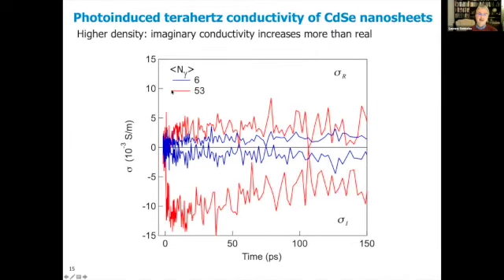Now, if you go to a higher photoexcitation density, so here in the red curves we excited 53 electrons in a nanosheet, so we make 53 photoexcitations. Then you see that the real conductivity hardly goes up. Well, it goes up maybe with a factor 3 or something, but the imaginary conductivity goes up much more. That is about, let's say, going here from a magnitude of 1 to about 10. So it's about an order of magnitude, proportional to the number of absorbed photons per nanosheet. So you see a completely different behavior or dependence of the real and the imaginary conductivity on the density of photoexcitations.